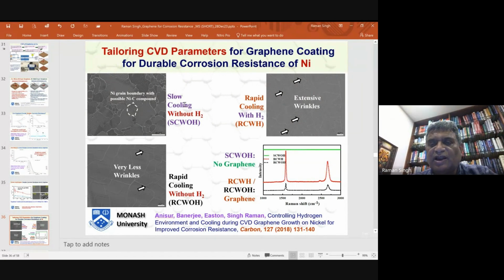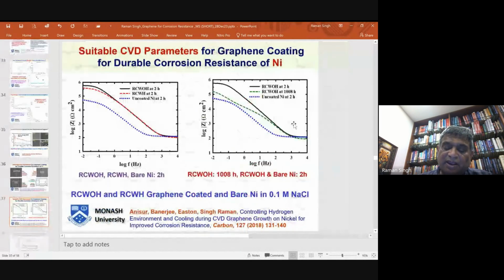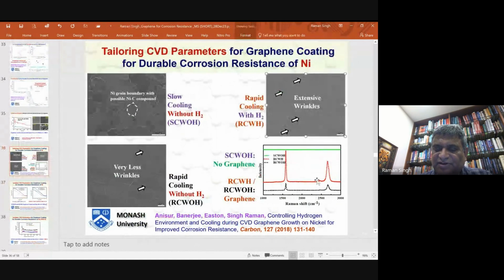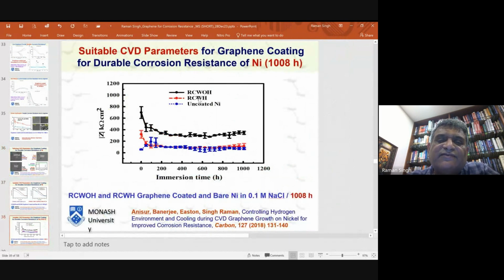And to cut the long story short, I don't have time to go into details. We could show that if you do rapid cooling after CVD, and in the environment without hydrogen, then you develop graphene with less wrinkles, and we don't want much wrinkles because wrinkles are bad for corrosion resistance. But if you did slow cooling without hydrogen, you end up not developing any graphene. Or if you did rapid cooling with hydrogen, again, not much graphene. And we could characterize that using Raman spectroscopy, as you can see here. And the graphene that is developed with rapid cooling after CVD and without hydrogen gave corrosion resistance that is stabilized after some time, and that corrosion resistance continues for more than 1,000 hours in this highly corrosive chloride solution.